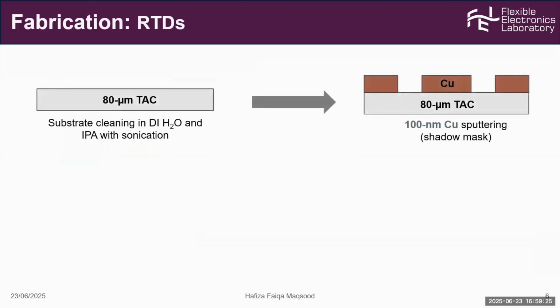We fabricated two types of temperature sensors. One is the RTD, and for this application, we start with 80 micrometer thick TAC substrates, and then we sputtered 100 nanometer copper as electrodes, and we used a shadow mask to define the deposition areas.